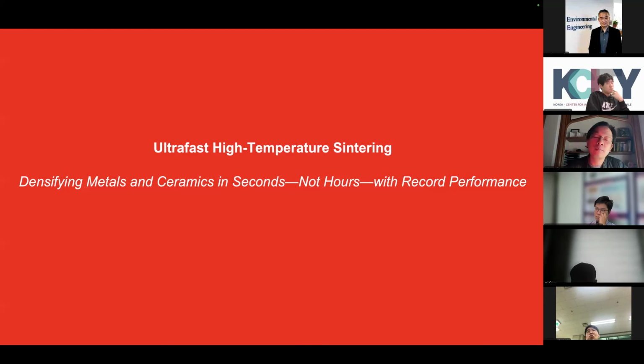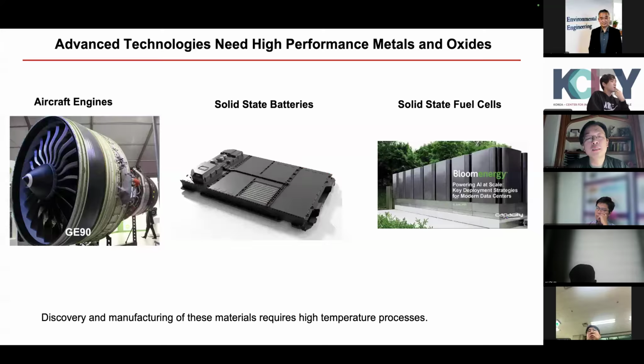At the same time, I'm also going to show you that using this rapid sintering, we can actually get even better performance in addition to faster speed. Now, why is that? Basically, in our process, we melt everything and we freeze it. We densify it right away, all together, in a few seconds.